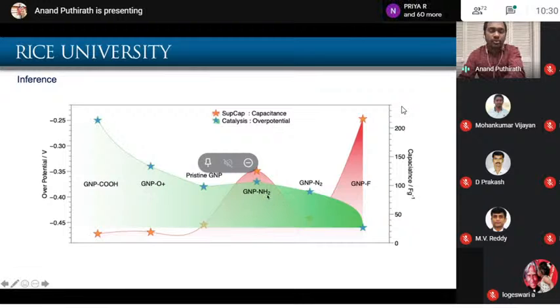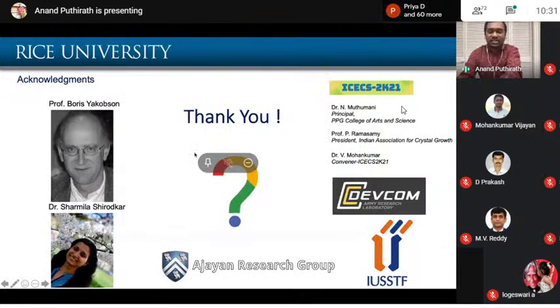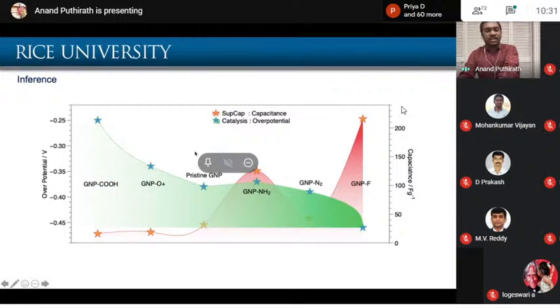And GNP amine functionalized, this can be easily converted into ammonia, because you already have NH2, and if you bring a hydrogen radical, that can form ammonia, and ammonia gas can be released, which we have not accounted for during this course of characterization, because we are only looking at water splitting and this kind of stuff. So this interesting complementary behavior is observed, and we communicated this to Nanoscale, and they reviewed and they are happy to accept it. And it's quite interesting, and it's probably helpful for people who work in this field.